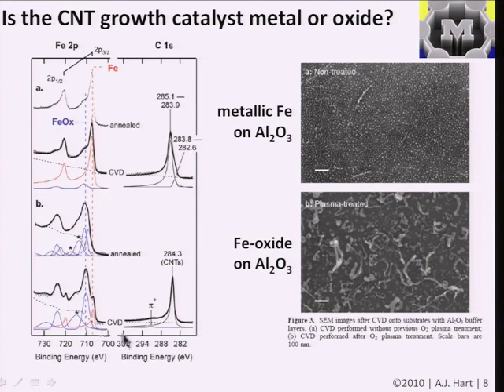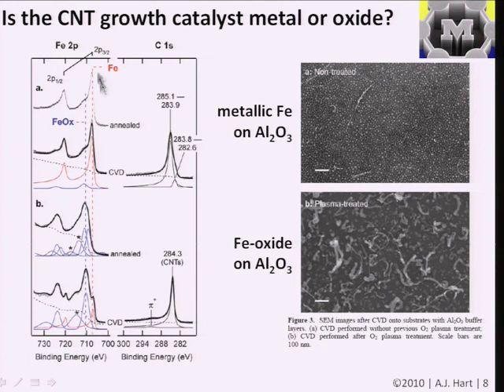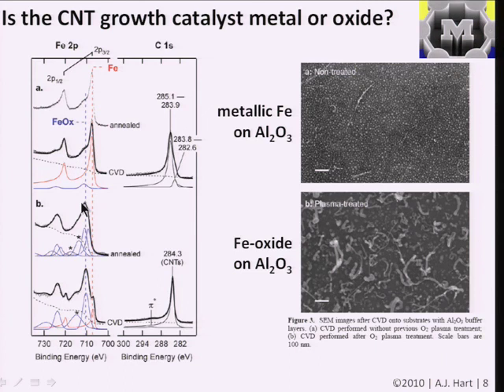Sample XPS spectra show a small window of binding energies versus intensity. They've labeled the position of an iron oxide peak with a blue line, and as the catalyst is annealed, it evolves more into a metallic iron state. There are also precise peak positions for carbon nanotubes or graphite — slightly different positions for planar graphite versus tubular graphite. This is an example of a technique used for surface and chemical analysis of materials.